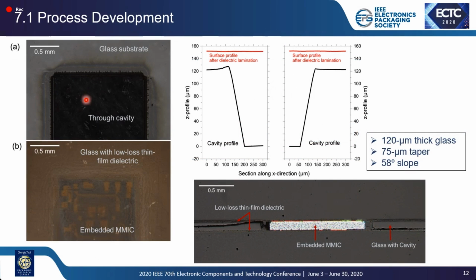So let me show you some characterization results. These figures are the top views of a glass panel with the cavity drilled. And this is a Z profile of the cavity. The thickness was 120 micron, and it had almost 75 micron taper, which is almost a 60 degree slope. And here is the figure of the MMIC and LNA embedded into the glass cavity with the low-loss film Taiyo Zeristo laminated over it.